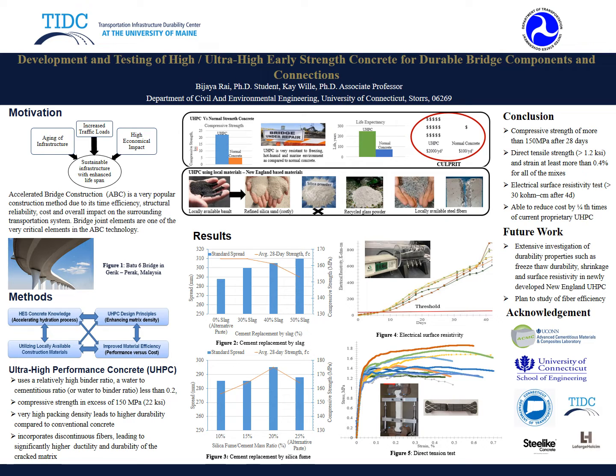Let's talk about the results now. As we can see in figures 2 and 3, all the concrete matrices have exceeded the compressive strength of 150 megapascal while having sufficient workability. Increase in slag replacement has slightly increased the strength and led to a decrease in workability, starting with 40% replacement. In terms of silica fume to cement ratio, you can see that the best workability and strength is at a ratio of 20%. There are results of electrical resistivity and direct tension in figures 4 and 5 respectively.